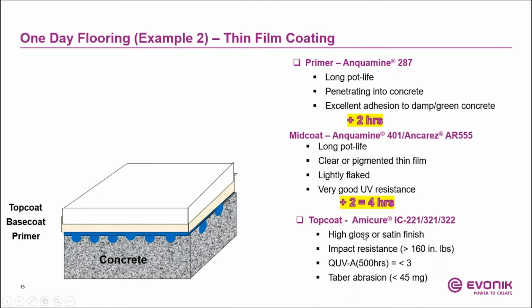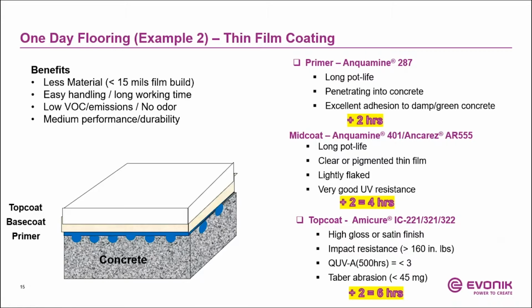So after 2 hours, you can put a top coat down. In this case, a top coat can be pigmented. So if you're using a clear base coat, you can use a pigmented top coat. If you're using a pigmented base coat, you can just seal it off with a clear top coat. And what you get again is the benefit of the polycarbamide technology, which I mentioned before, a very durable type of coating. Again, 2 hours later, a total of 6 hours, you're done with the job.